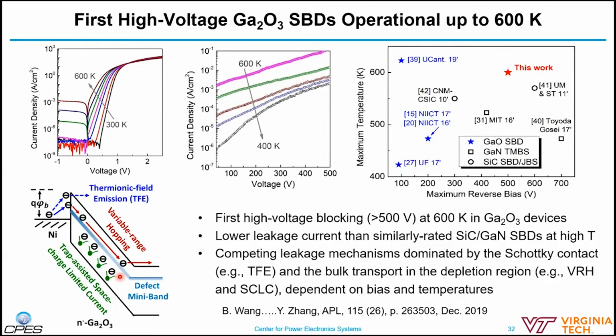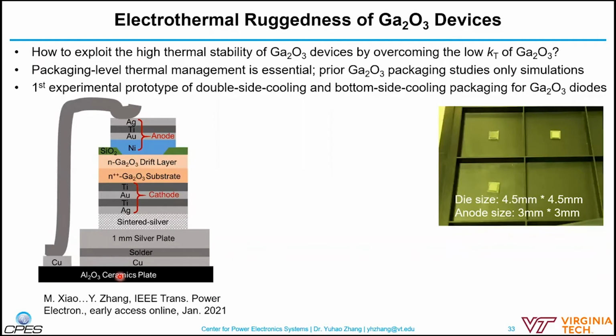So from that, we had a feeling that those gallium oxide devices are potentially very stable, or at least have better thermal stability compared to silicon carbide and gallium nitride devices, probably benefiting from some of the inherent properties of ultra-wide bandgap semiconductors. So how do we exploit this potentially high thermal stability of gallium oxide devices, while overcoming the fact that gallium oxide itself has a very low thermal conductivity? That's like 1/10 of silicon and about 1/20 of silicon carbide. So packaging-level thermal management is essential.